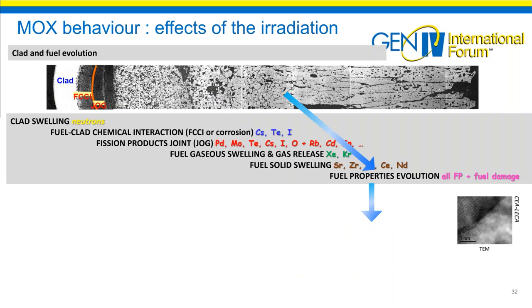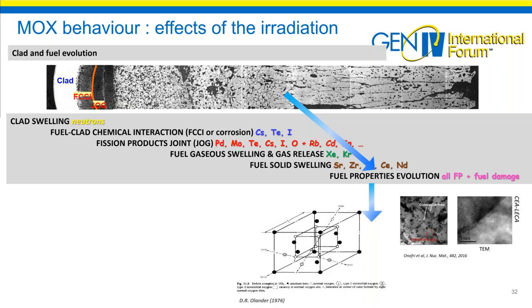So very quickly, because I spoke about the properties, all the mechanical and thermal properties are affected by the radiation, not only by the fission product inclusions, but also by the disorder in the structure due to the fission reactions and the recoil of the products, but also due to the neutron effects. We also have to take into account the evolution of composition, stoichiometry, and density on these properties. And we have several devices in order to evaluate this damage coming from the irradiation, especially the TEM. So next slide, please, on the thermal behavior of the fuel element.